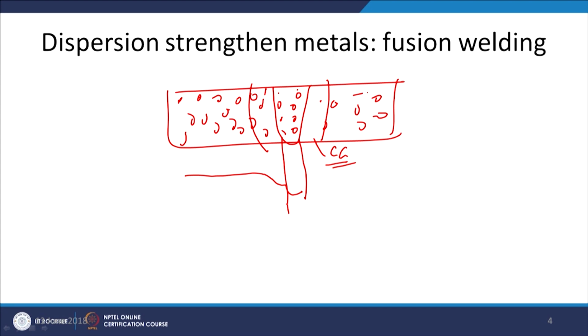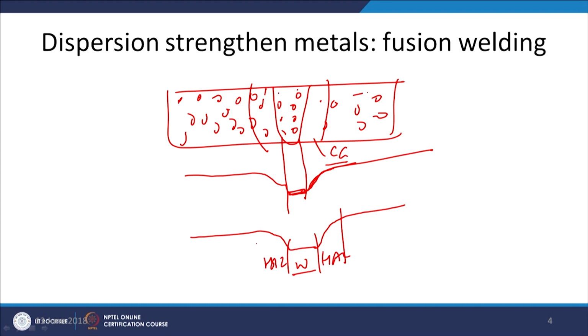There will be thermal damage to the reinforcing agent. So, the properties may be significantly lower in the weld zone, while on the other side again the properties may be compromised in the heat affected zone due to the grain coarsening. So, there can be soft zone formation in the heat affected zone as well as the weld zone, and then gradually increasing hardness on the other side. So, this is how we can understand the weld zone, HAZ, both the sides, and then the base metal. This is how the dispersion strengthened metals can behave.